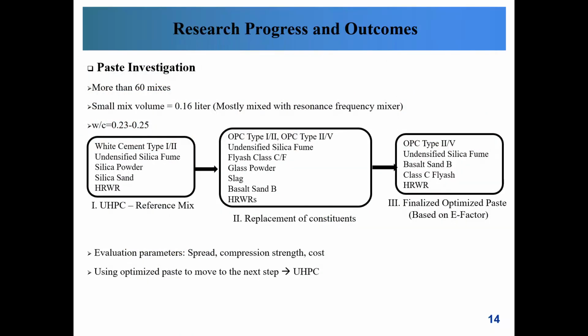Research progress and outcomes. Besides our progress in enhancing our test setups, we have significantly progressed in material testing. So far, more than 60 paste mixes have been performed, usually small volumes of 0.16 liter, mostly mixed with the resonance frequency mixer, with a water-to-cement ratio of 0.23 to 0.25.